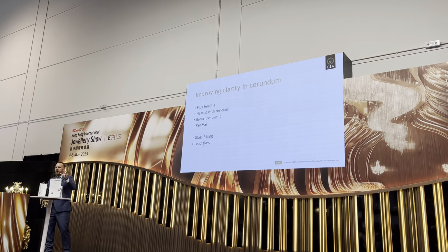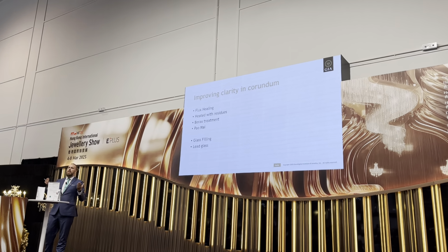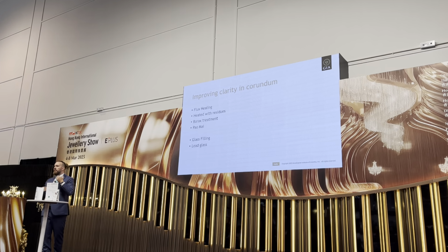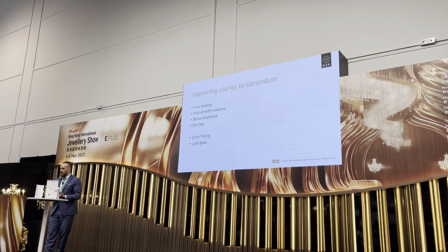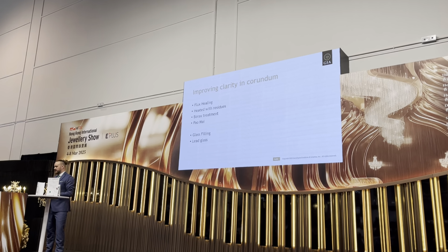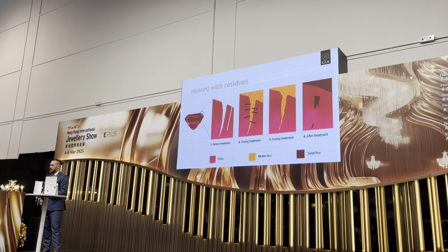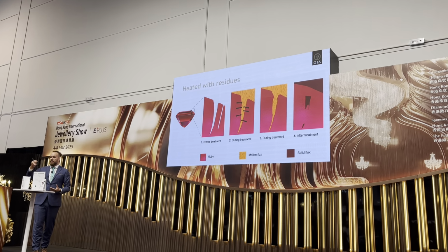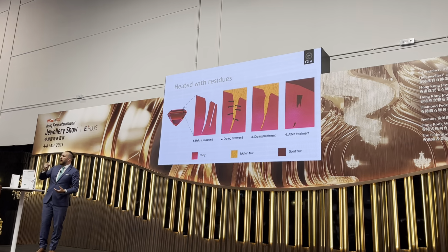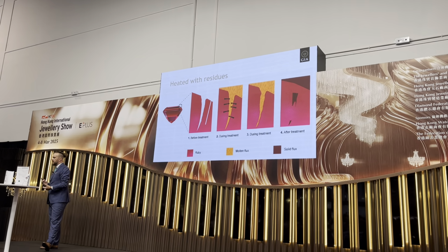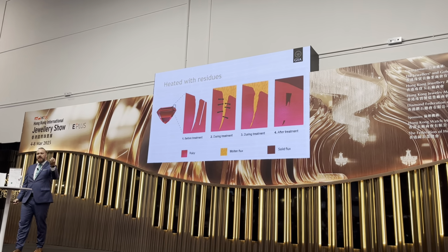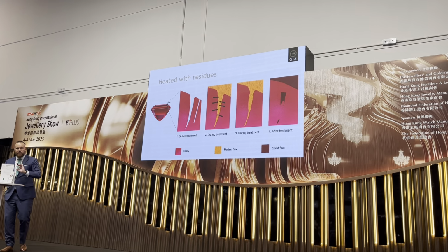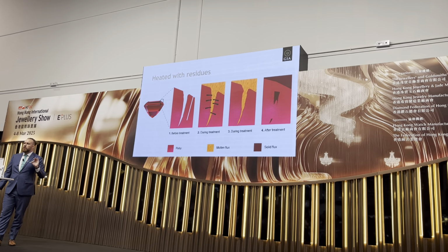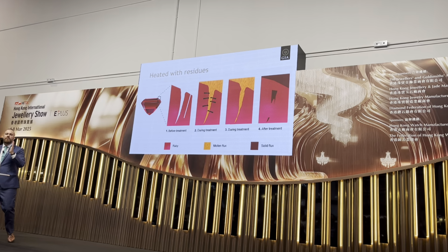So those are two different treatments with the same goal in mind, and that is working on the fractures in your corundum, trying to mask the fractures there. So we're going to start with the first one, and that is heat with residue with flux. And it is actually a very complex process that happens there, but basically by adding flux, by putting flux into your fractures, you are able to heal your fractures completely.